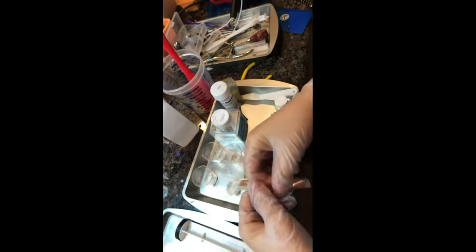The strange thing about adding glitter to the pigments is that it actually changes the behavior of the silicone, because now you've got these plates inside the silicone mixture. So when the molecules stretch out, they've got plates that they have to kind of wrap around, and it actually makes the silicone a little bit stiffer. So that's a really funny change in property by adding glitter. The particulate of the flakes is enough to change its behavior from an elastomer into a composite. Whereas the fine particles like this, they are like nano-sized, but